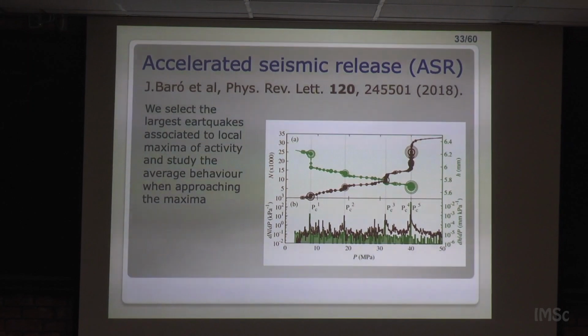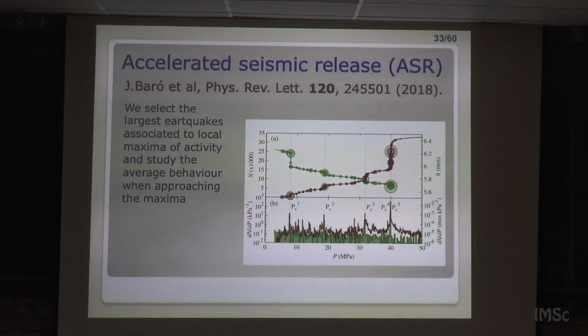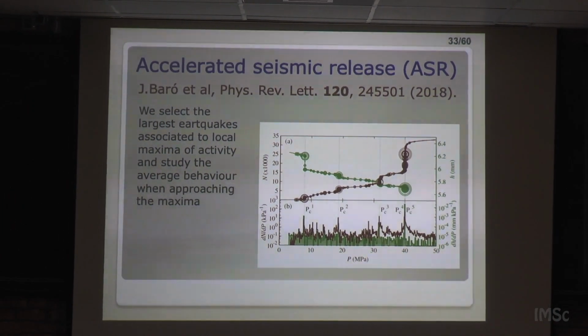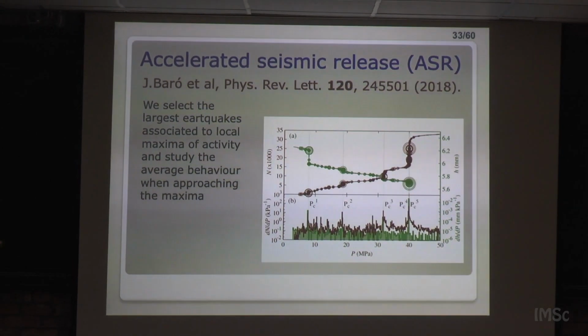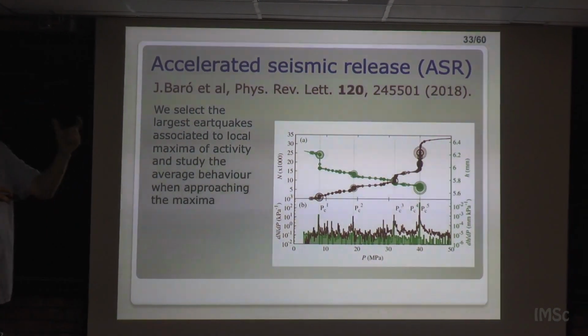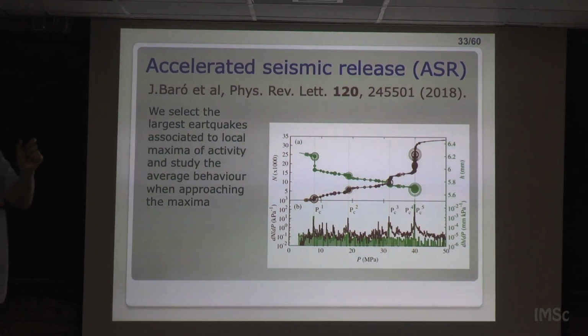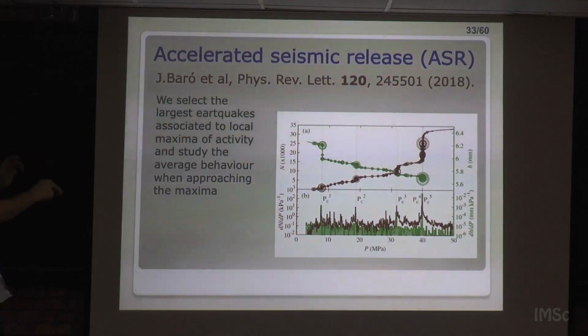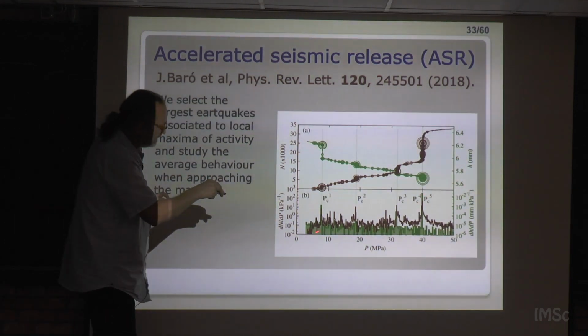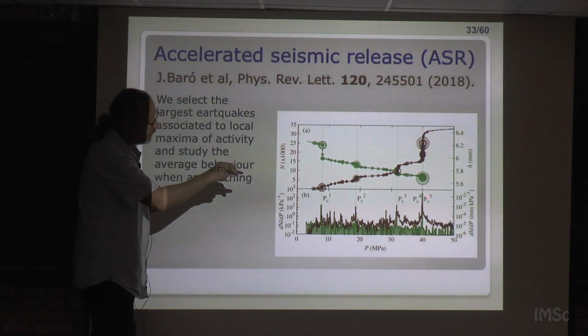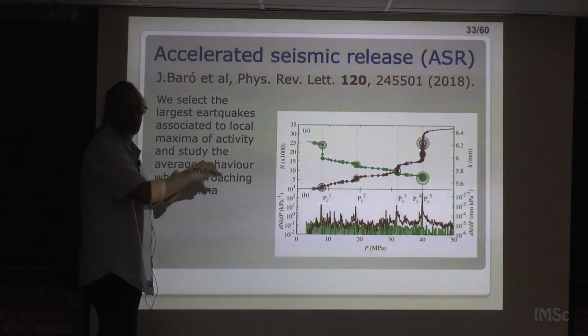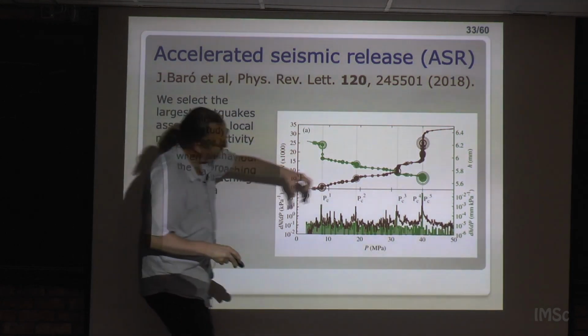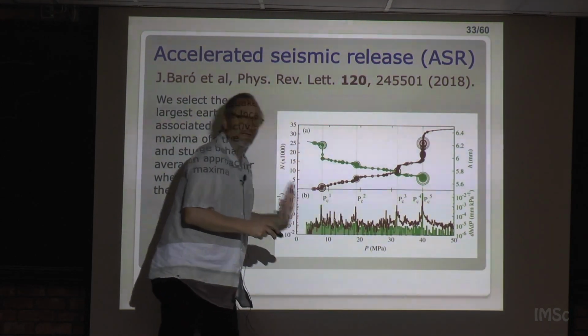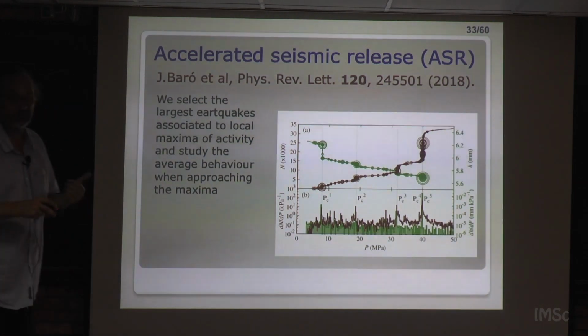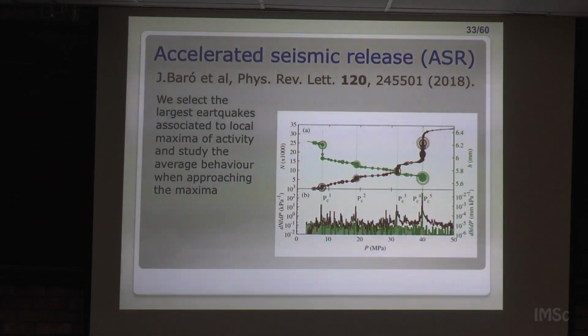Okay, something that we studied recently in this paper with Jordi Baró from the Mathematical Center near Barcelona is not to take windows like this at random, but just to take windows that end in a big event. So essentially, we recognize in this sequence of events where the big ones are, in this case the five big ones, and then we consider the approach to this event, the approach to this event, the approach to this event, and the approach to this event, and we overlap that, and we make the statistics. So it's like trying to study the foreshocks.